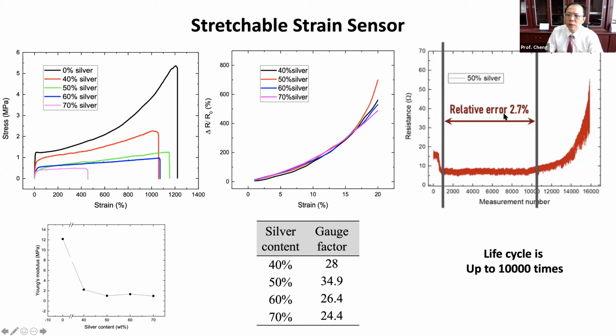The relative error is only 2.7%. So our gauge factor is quite high compared to the other literature. You can see the gauge factor goes to 30. That means our sensor is very sensitive.